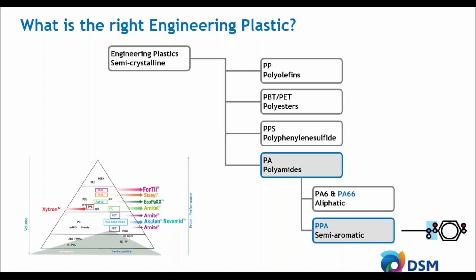Actually, in the polyamide family, you have two different subsegments. The first one is the aliphatic polyamides, polyamide 6 and polyamide 6,6. Especially polyamide 6,6 is one of the key materials being used, and we also will use that as a benchmark during the comparisons with aluminum, but also with the PPAs that we are going to introduce. The second part are the semi-aromatic polyamides, the so-called PPAs, polyphthalamides, where a ring structure is introduced in the polymer. And with that ring structure, you gain a few features that are very relevant if you want to replace metal with an engineering plastic. And we will dive a little bit deeper into that field.